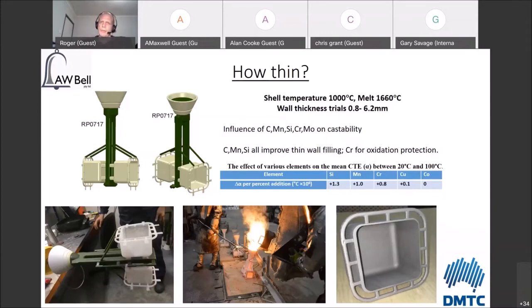So what we looked at with this was the influence of carbon, manganese, silicon, chrome, and molybdenum on castability. Knowing that carbon, manganese, and silicon all improve thin wall filling. A little bit of chrome was kept in there, mostly for oxidation protection. Even 0.1% chrome can give you some reasonable protection in your material, and it tends to change the amount of slag-forming oxides that you have to deal with along the way.